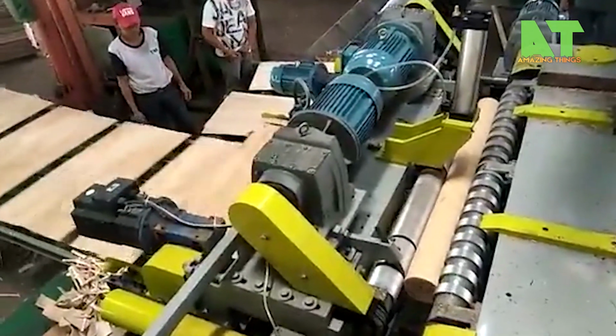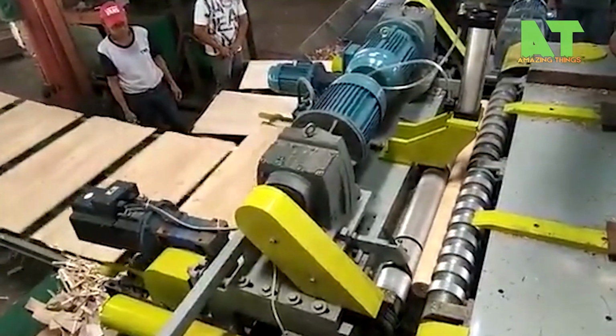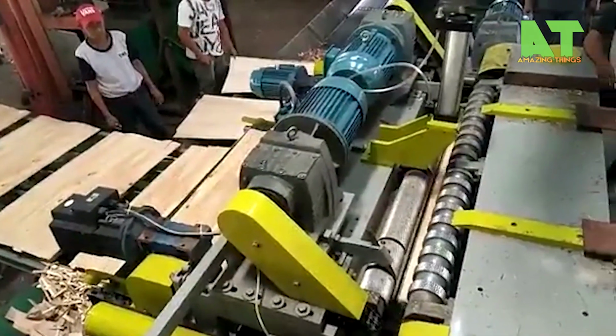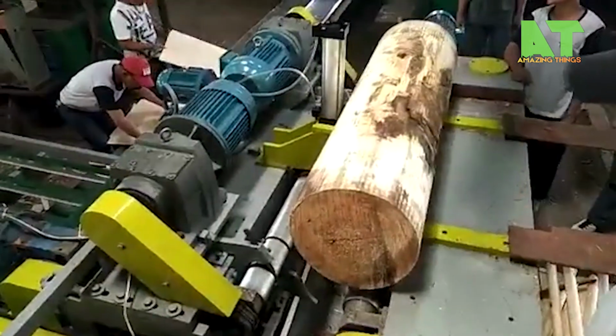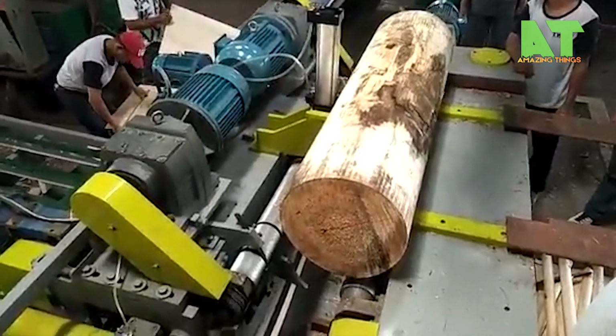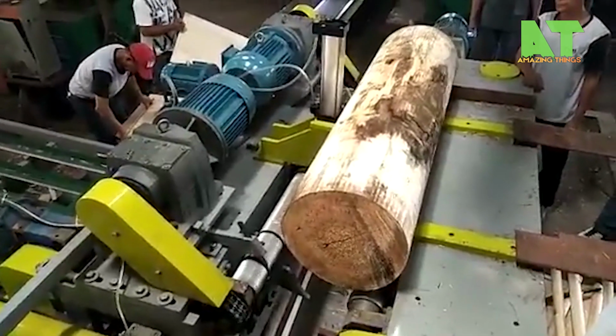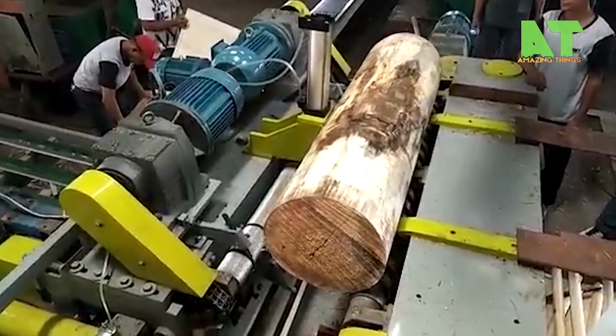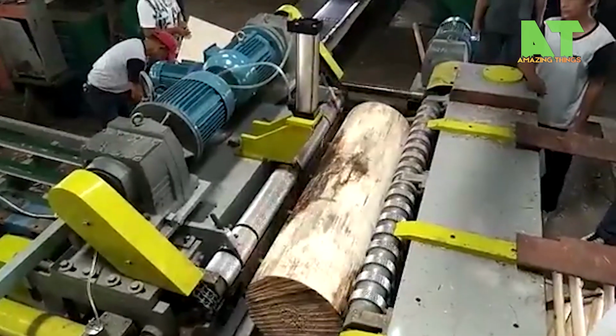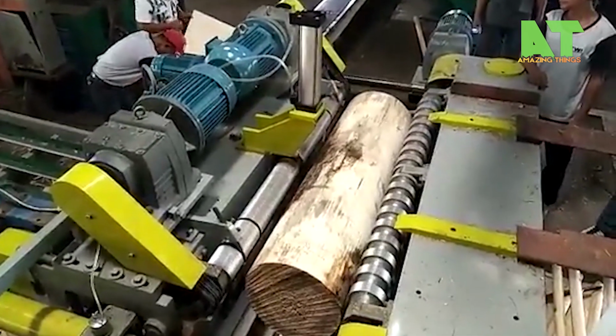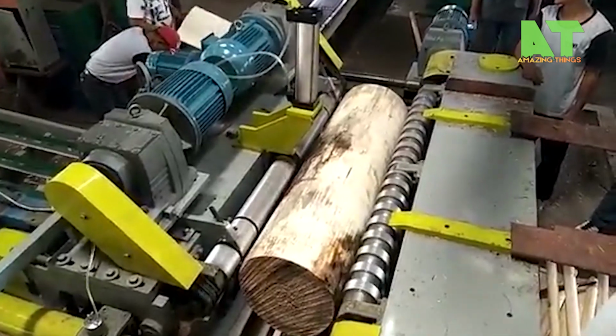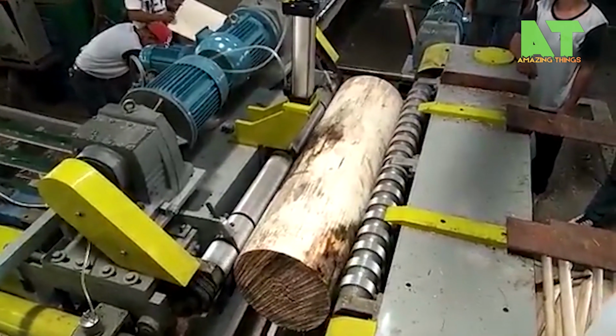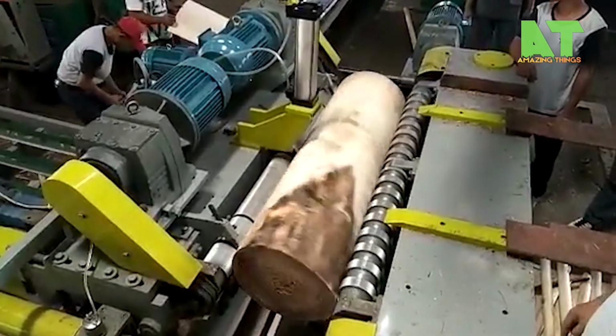As the log's diameter gets smaller during peeling, the machine automatically increases the rotation speed to maintain a constant surface speed at the cutting edge. This keeps the veneer thickness perfectly uniform, usually between 0.5 mm and 3.2 mm, from the first peel to the last. Without this compensation, the veneer would taper unevenly, creating waste and weak spots in the finished plywood.